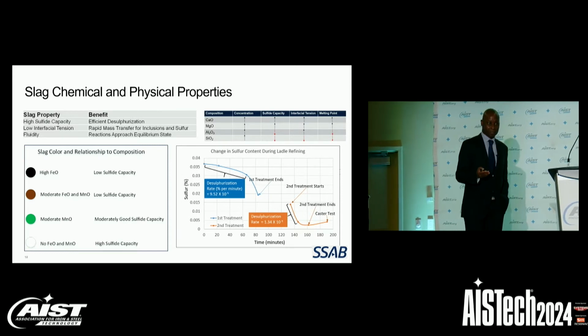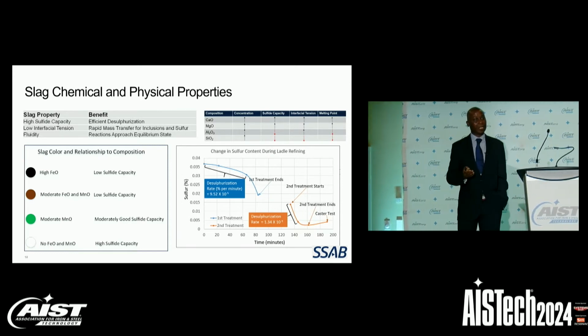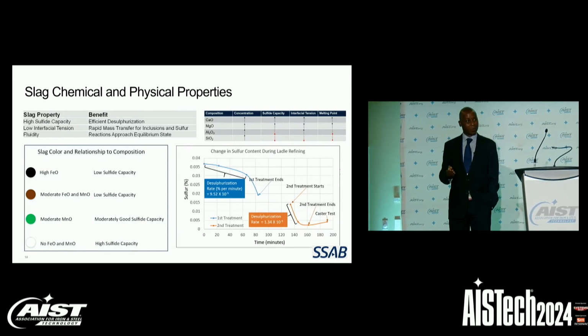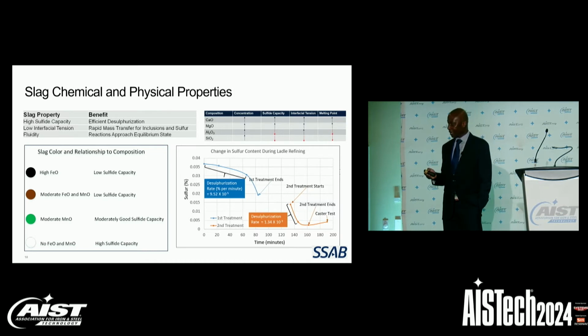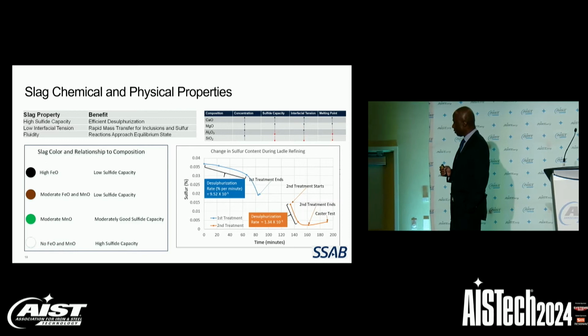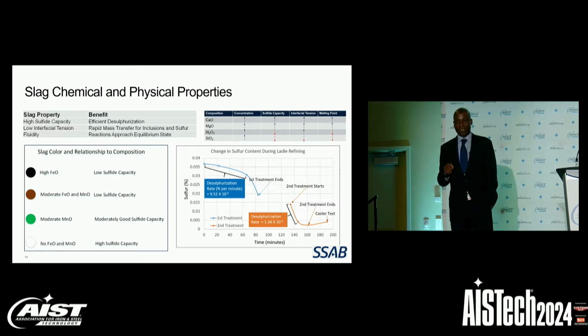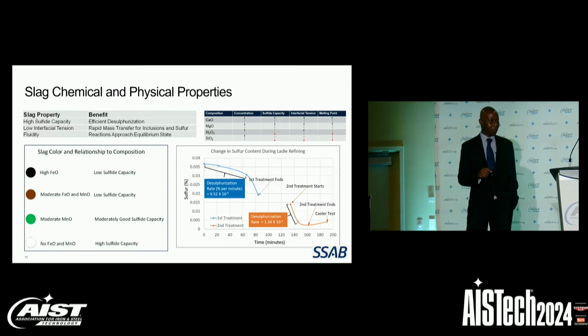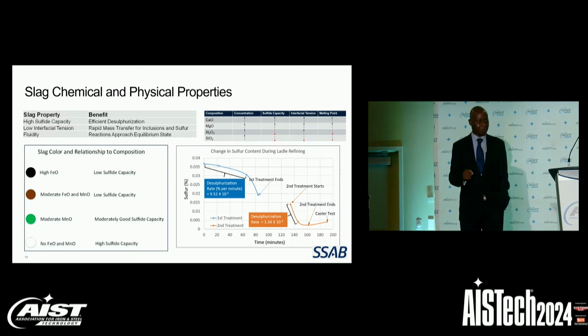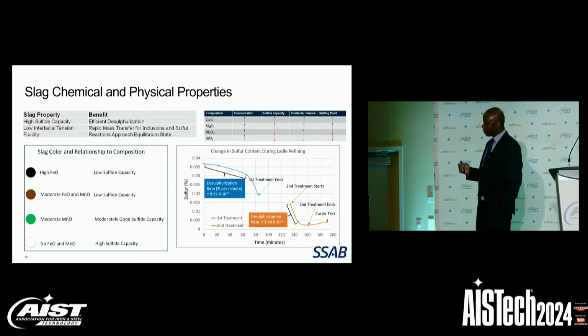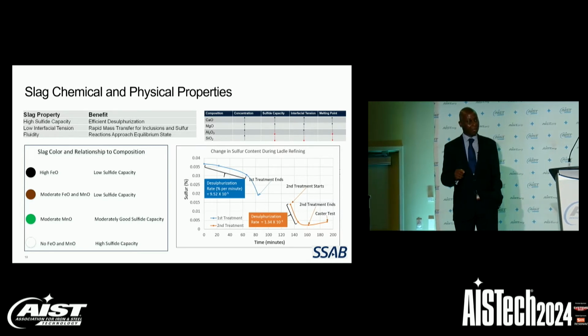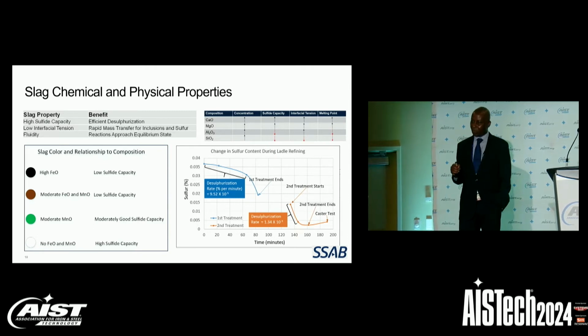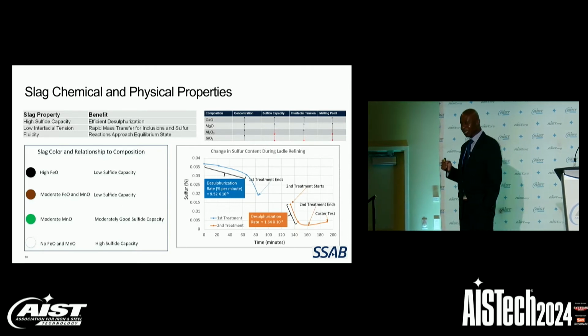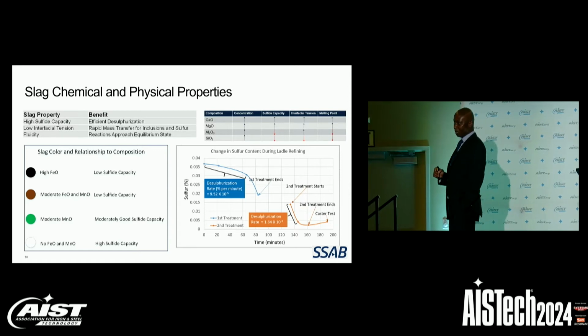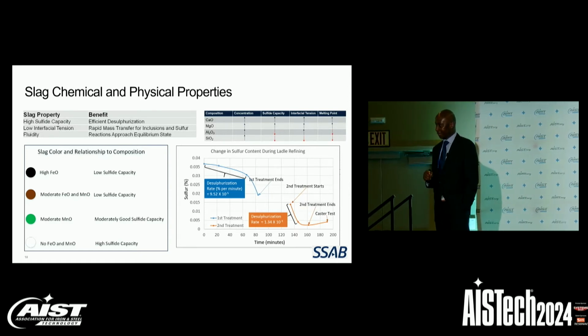Unlike the steel, it is operationally inefficient to sample the slag for chemical analysis during the refining of steel in the ladle. But fortunately, the slag does change color as its composition changes. And operators rely on this change in color to determine whether they have a good slag or not. But this doesn't always work the way we want it to.